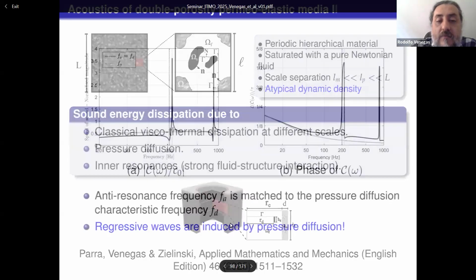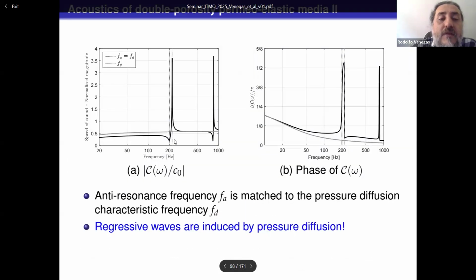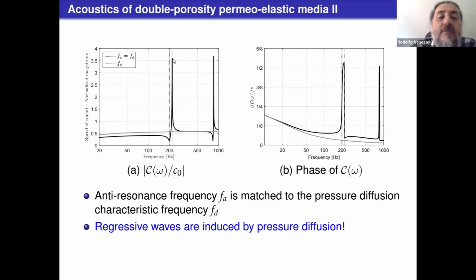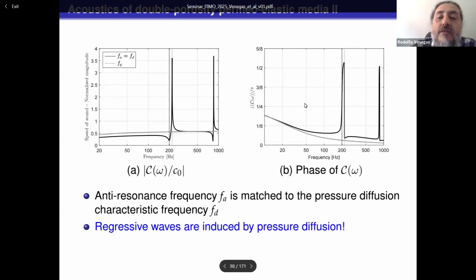An example of the speed of sound is this one. There's a reduction in speed of sound, and then a very sharp increase in speed of sound leading to supersonic velocities. And pressure diffusion, in particular, when we match the anti-resonance of the plates and the characteristic frequency of pressure diffusion, induces regressive waves in between these two characteristic frequencies. Without accounting for that, we wouldn't predict these regressive waves.